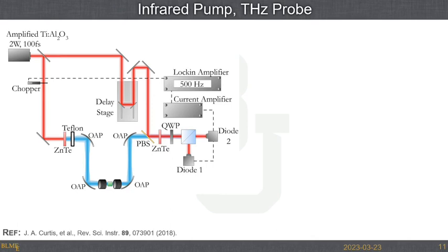If I've made changes to, for example, the speed of light in the material somehow here, then this path is going to be slightly longer than that path, and I'll see the interference between the 2 of them. And so I actually have a computer-controlled stage here, but really I'm taking these 2 pulses, breaking them apart, and combining them back together again. But if I make changes to my material, I can pick them up because of the slight path length difference. So the speed of light, we all know, is 3 times 10 to the 8th meters per second, or 0.3 millimeters per picosecond. And so if I can have very fine control over all of this, I can get these very fast processes in materials because I'm looking at how these pulses combine.